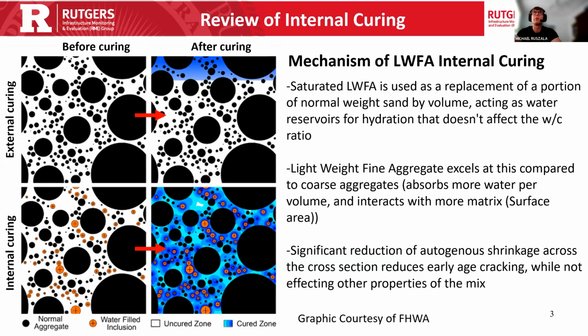typical external curing only affects the top surface. HPC is a very dense material. It's not very pervious. So it doesn't get a cure throughout, or additional effective curing throughout the cross section. So this can result in a gradient, can result in different stresses developing, and increases cracking potential effectively.